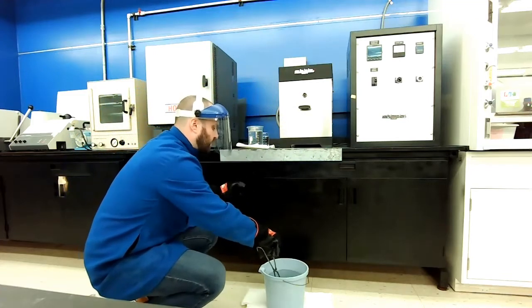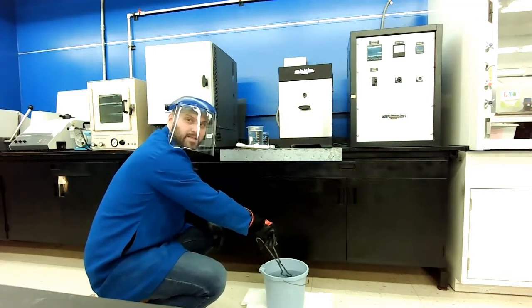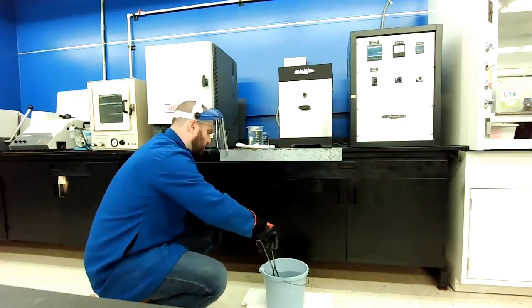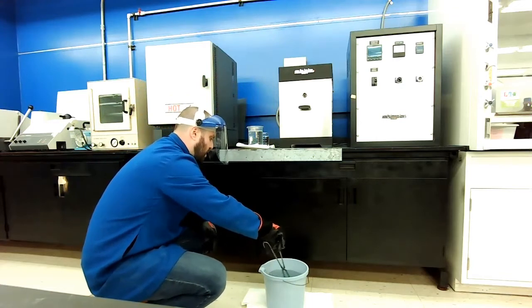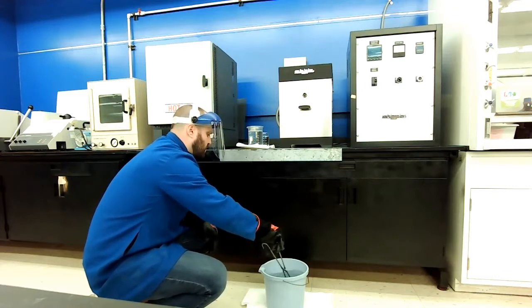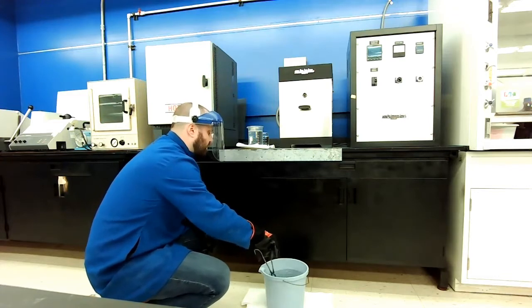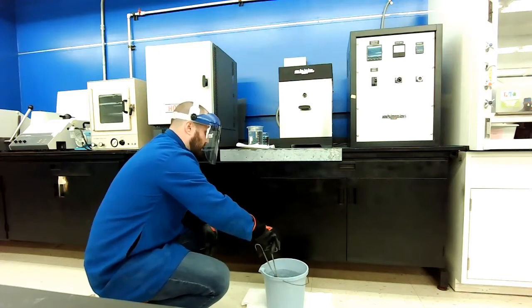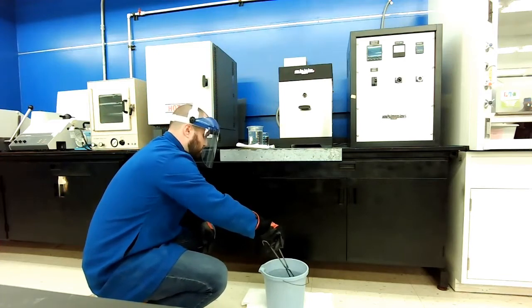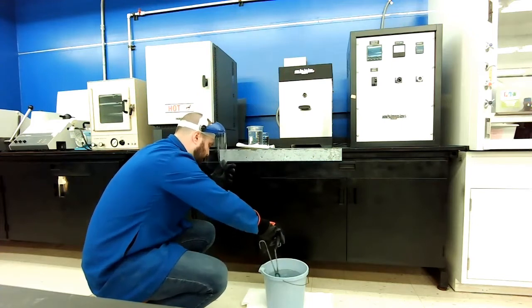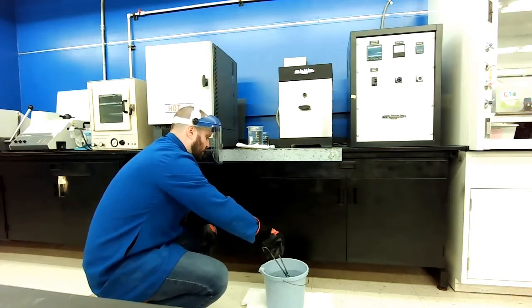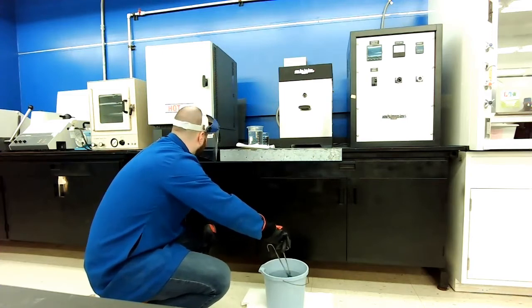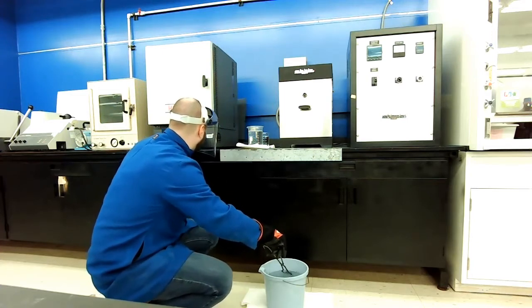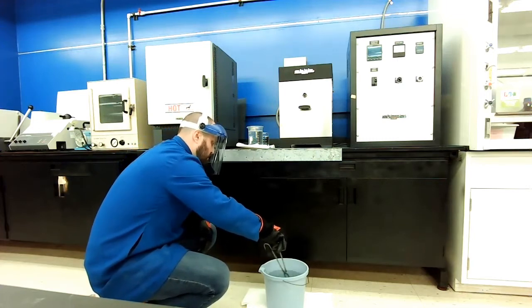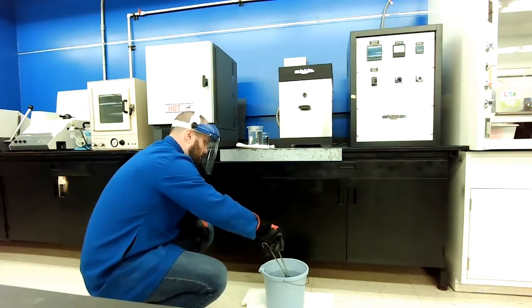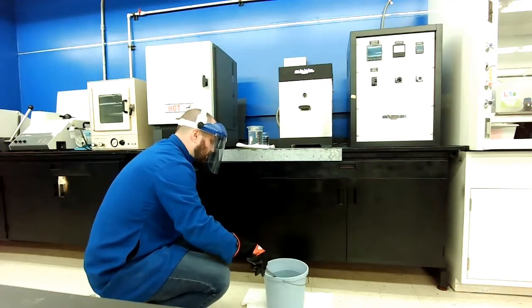So we still heard that large change in temperature. I'm mixing this around to try to not allow that air pocket around the sample to form. But it was a lot less aggressive. The sample was not quite hot this time. So, a visual representation of the fact that we were at a much lower temperature. Right? I'm not seeing any air bubbles.